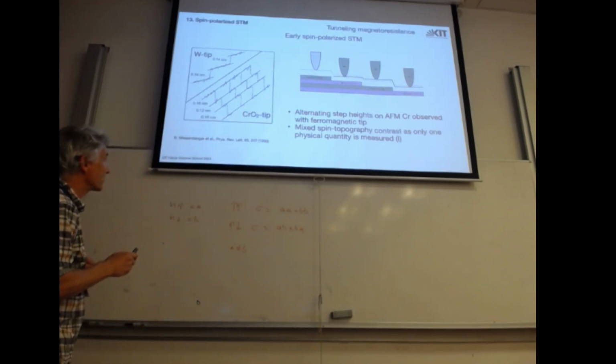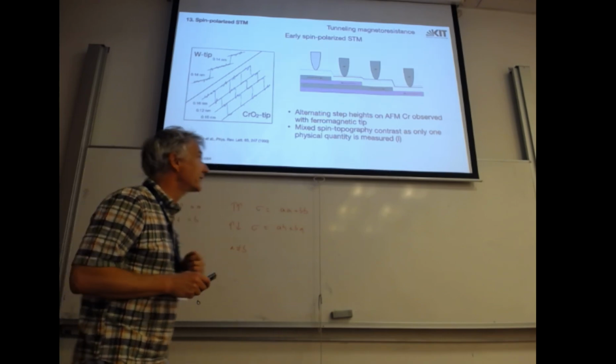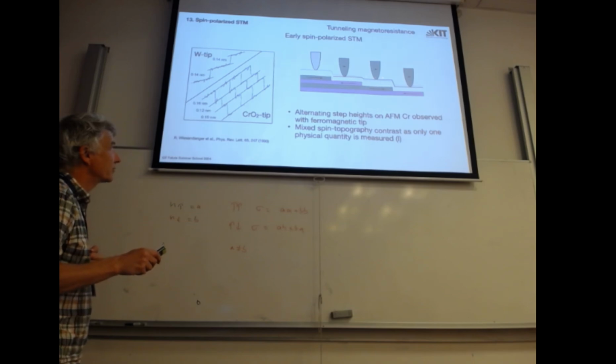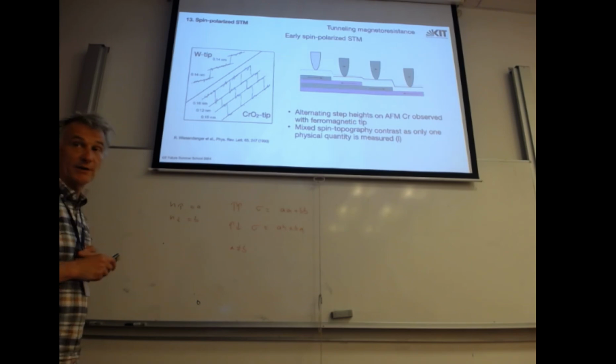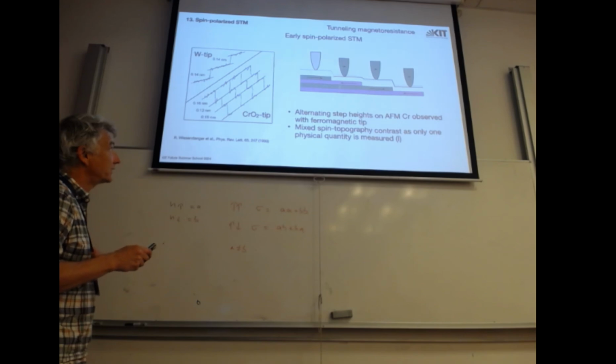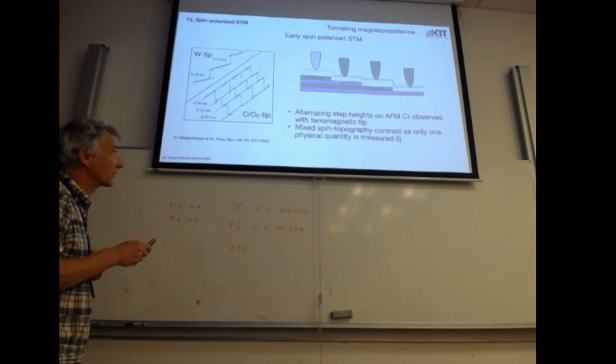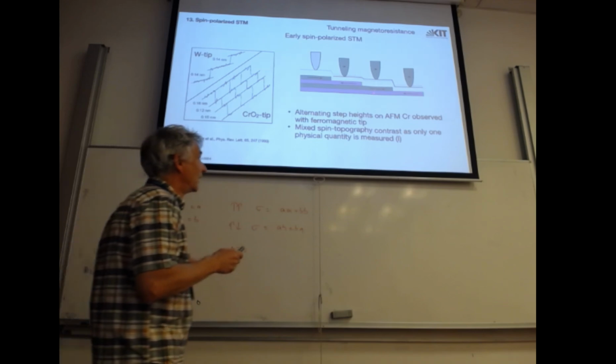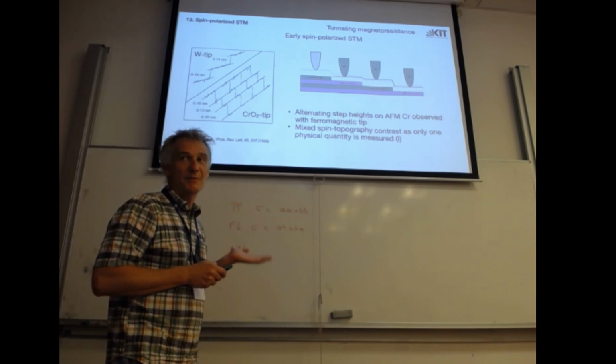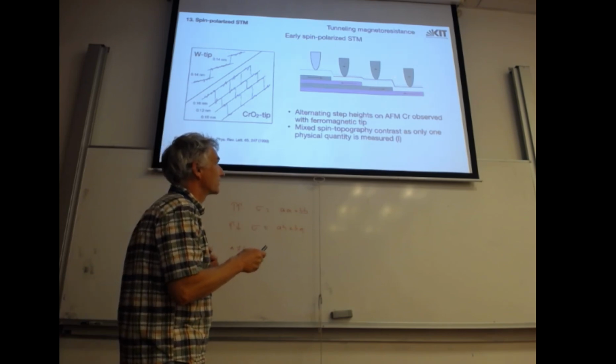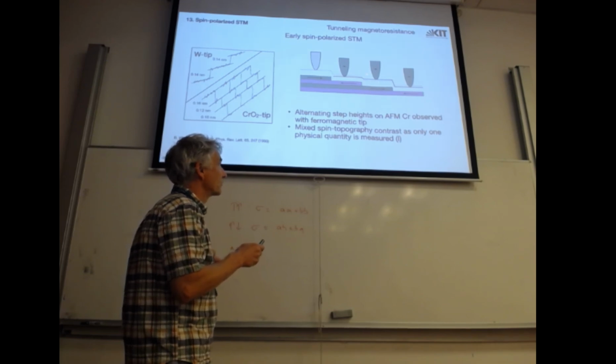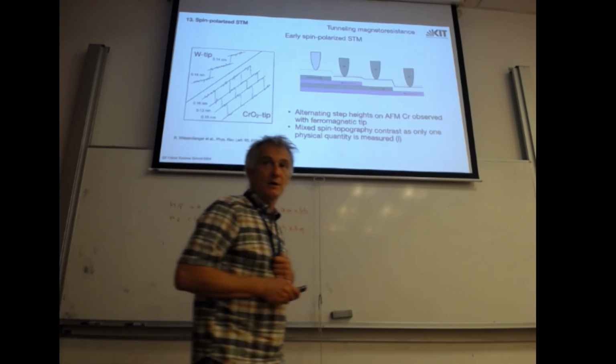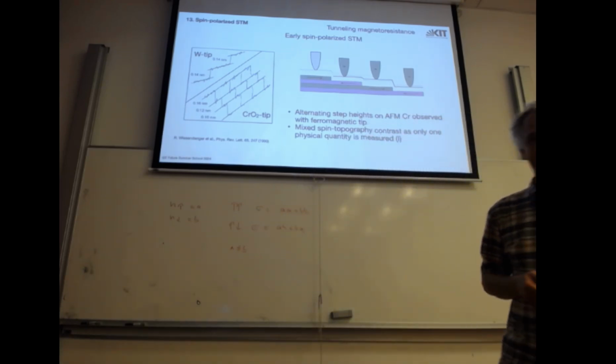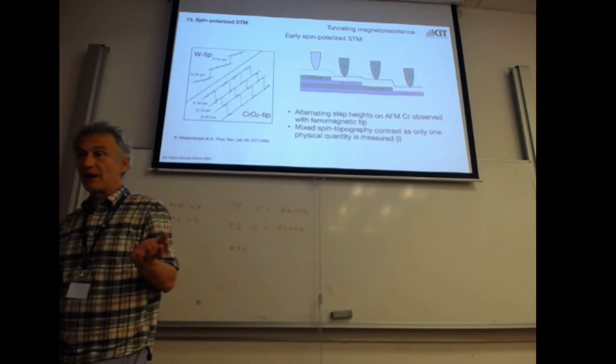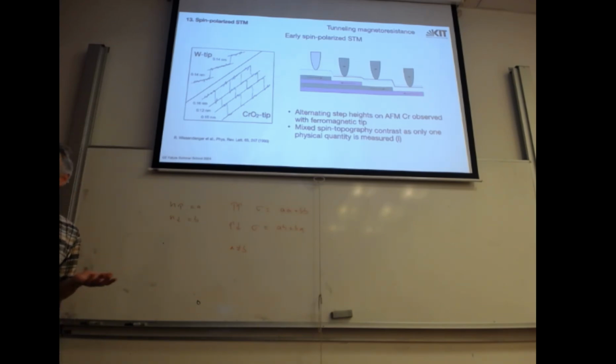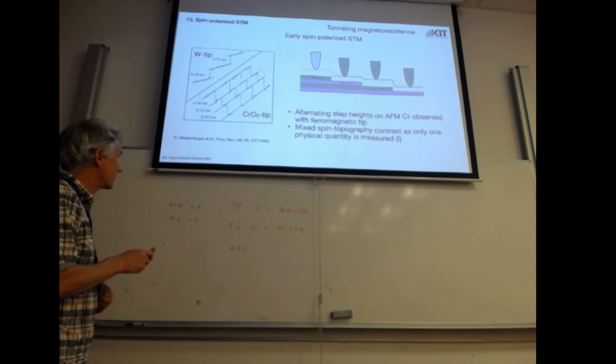But if you use a highly spin polarized tip, chromium dioxide is almost 100% spin polarized, and he repeated the experiment, he saw a small step, large step, small step, large step. So this is here. Why? If they are anti-parallel, the current is smaller, or the conductivity is smaller, so the tip will go a little bit closer to the surface to obtain the same tunneling current. And if the two magnetizations are parallel, the conductance is higher, the tip is a little bit retracted over the polarized position, and then there's a small step here, and a step up, and a large step here. So mixed into the topography is spin information. But in principle, you cannot tell if the steps are different in height or if there's spin polarization. Both cannot be distinguished. So actually, this spin polarization rested for some time